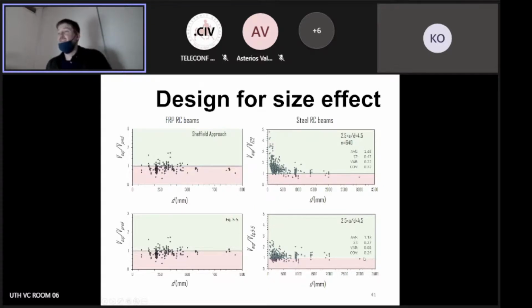This is a really huge improvement to the existing code, because if this is the performance of the existing Eurocode equation, which should make that set of data points along the line, it clearly doesn't. You can see the same size effect that I was showing you at the beginning of this presentation. If you use the equations that we developed at the University of Sheffield, you can really bring this a little bit down and make this design more economic and robust.